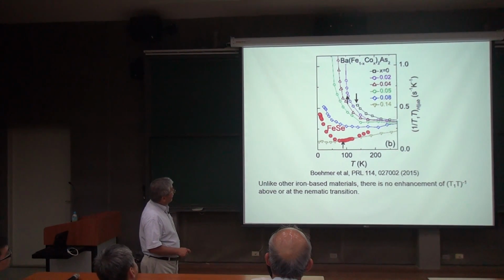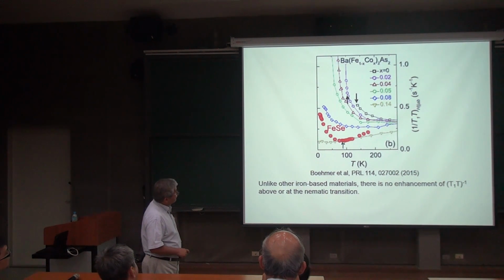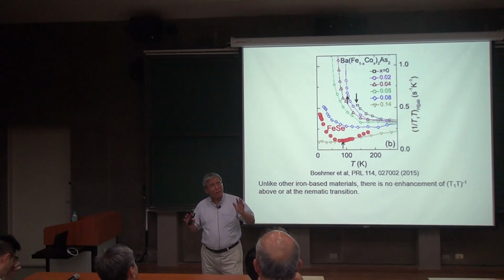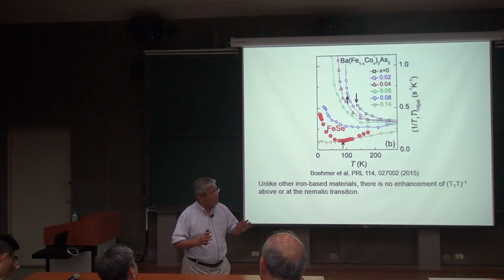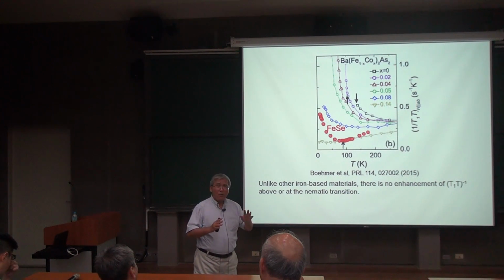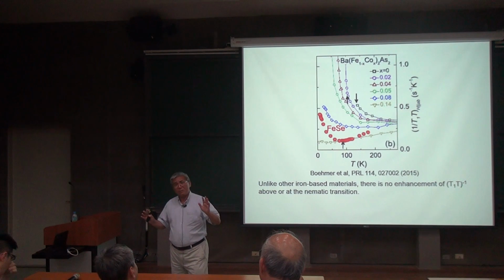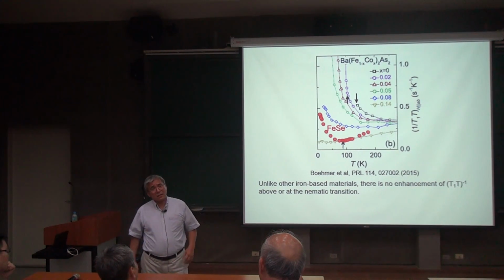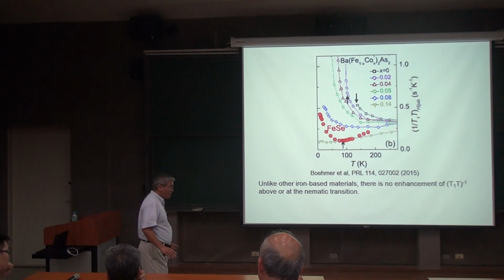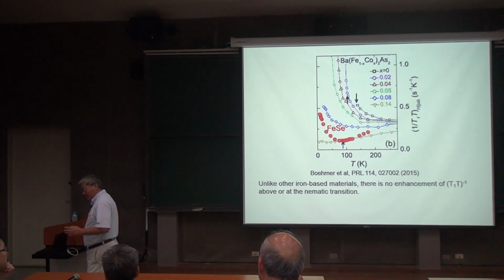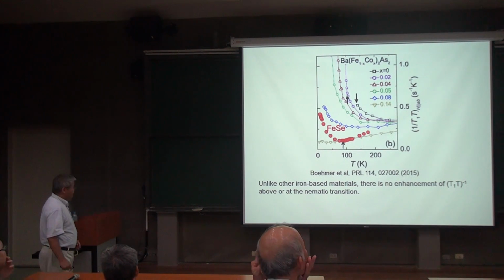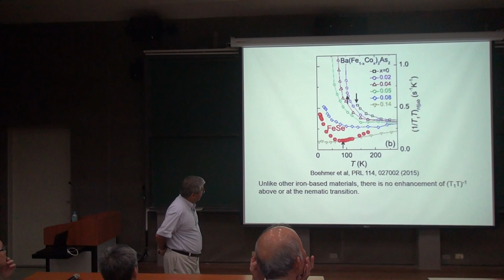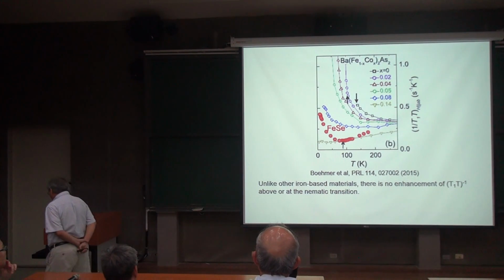Now, however, for iron selenide, here is where the structure transition occurs. Not only has the magnetic fluctuation 1 over T1T not been enhanced here, but it is at a minimum here. It's only below the structure transition that it begins to be enhanced. So at this point, there's no doubt among experimentalists that the nematicity in this system is driven by something other than magnetic fluctuations. We see many papers stating that we definitively prove that iron selenide nematicity is caused by orbital fluctuations. At this point, the orbital fluctuation school has enjoyed utmost glory, and they claim that actually all the high-temperature superconductivity in iron-based superconductors is also caused by orbital fluctuations.